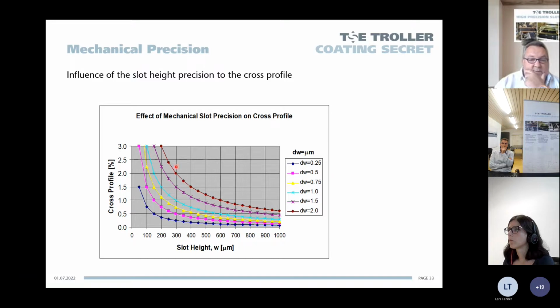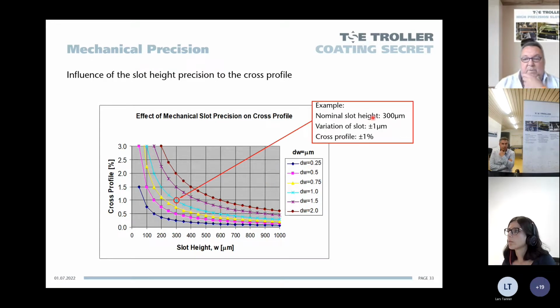Here is an example shown. Here you see the slot height, and this is the cross profile. And the parameter here is the slot uniformity or the variation in the slot. And as one example, for a 300 micron slot, the variation of plus minus 1 micron causes a cross profile of plus minus 1%. And this is without the impact to the rheology, so it might even be worse.